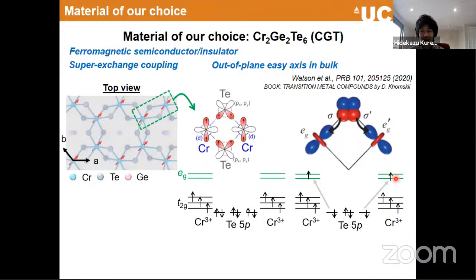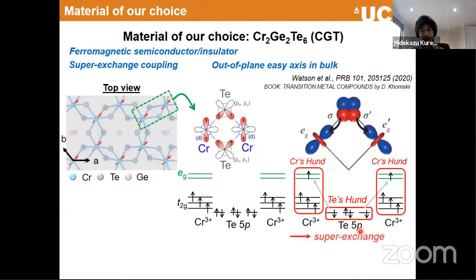And what happens here is that because of the tellurium Hund's rule, we want to polarize this S as big as possible. That's the first rule, that the sign of the spin polarization has to be the same for these two spins as described here. Now, we also have the local chromium Hund's rule. We try to polarize in the same direction as the tellurium, and because of this mechanism, we can drive the exchange interaction as a whole. So that gives us the mechanism of superexchange interactions, and that can give us a long range order, in this case, ferromagnetic order in the CGT.